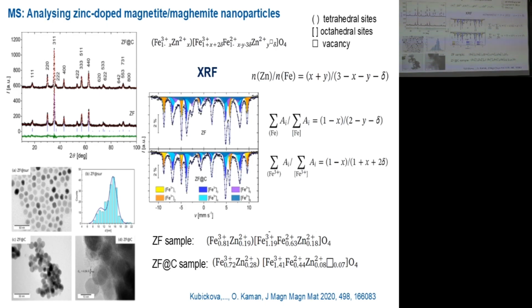It might be fine, because this is the total iron in tetrahedral sites, this is the total iron in octahedral sites, and this is the iron 3+ in tetrahedral sites, and this is the iron 3+ in octahedral sites. There can also be a different approach. You can quantify the ratio of iron 2+ and iron 3+, or iron 2+ there and here. But this is also independent.